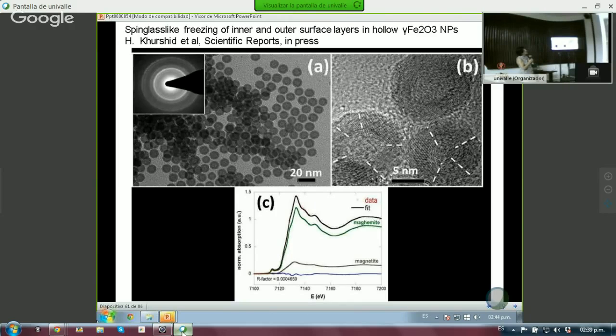This is a paper which was just accepted in Scientific Reports. And this is our work. In this case, we made hollow gamma iron oxide nanoparticles. And this is quite interesting because look here, A gives you a typical high resolution TEM. And now with B, you can go further, increase the resolution, and you can have much more detail about the nanoparticles.